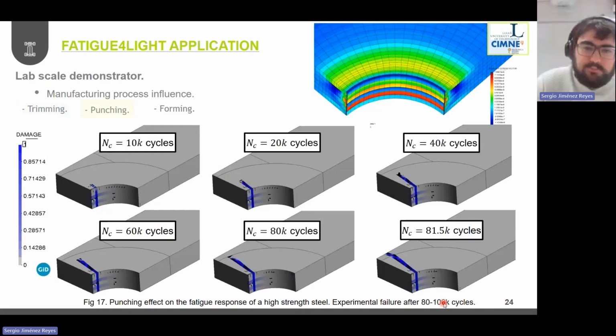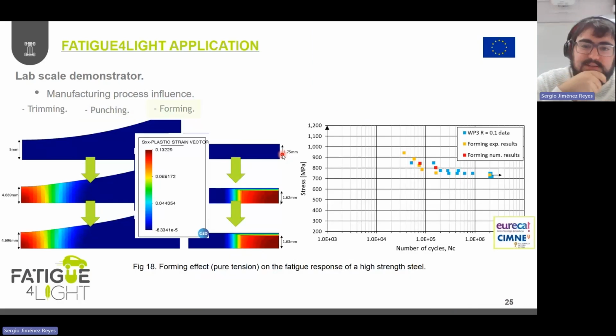Then we also work on punching cases where we introduce residual stresses in this punch area. And again, using the virgin material properties and introducing these residual stresses, we run the simulation and we obtain this new failure path, which really matches the information reported experimentally. And finally, we also worked on some forming cases. In particular, what I'm presenting here is a case where we first introduce a tensile deformation in the sample, and the sample experiences some plastic strains.